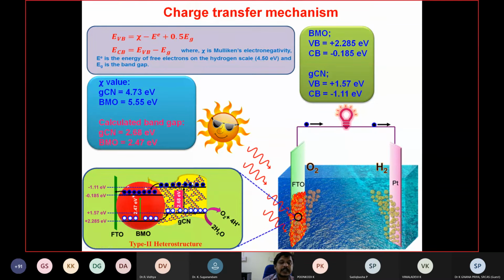Then the electrons move to the conduction band of bismuth molybdate and reach the FTO. That electron will move through the circuit and reach the counter electrode. Then the proton moves towards the counter electrode, accepts the electron, and finally you are able to produce hydrogen. So by oxidizing the water, you produce the oxygen evolution reaction. As a complementary reaction, you get the hydrogen evolution reaction. Okay, so that's all about this bismuth molybdate and graphitic carbon nitride heterojunction.